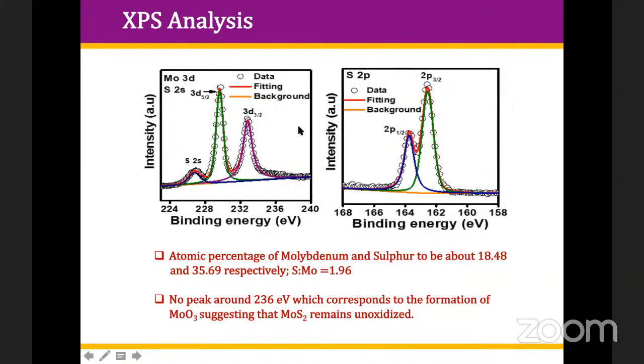We also perform, just to see, the compositional analysis of the MoS2, whether stoichiometry or composition has been maintained or not. So this is XPS of the molybdenum, and this is the XPS of sulfur 2p. And by composition, what we find out is that molybdenum has 18.48 and sulfur has 35.69. That means the ratio of sulfur to molybdenum is around 2. So that clearly shows that MoS2 has been formed.